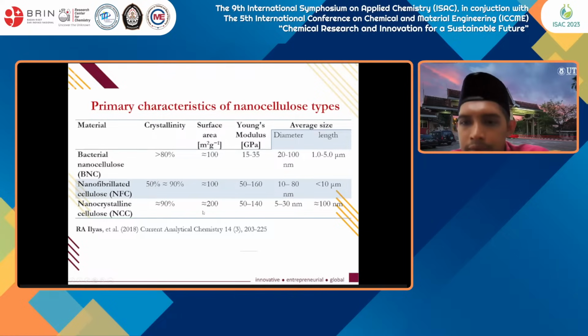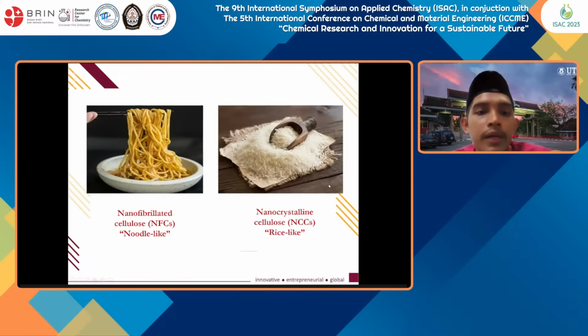If you look at the size, the size of the nanocrystalline is quite low, short. The size of the fiber is short compared to the nanofibrillated, which is up to 10 micrometers, and the bacterial cellulose is up to 1 to 5 micrometers.